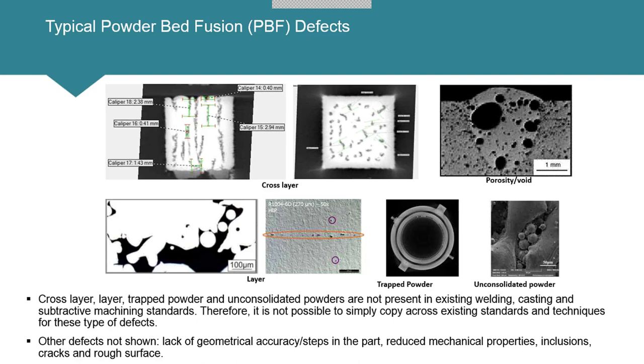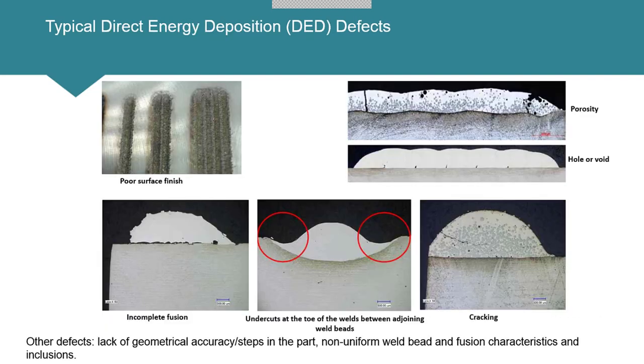Then you've got layer defects, and we also have trapped powder and unconsolidated powder. Trapped powder basically is powder that, for the geometry that was designed, gets trapped. And it may or may not be a problem, and therefore we may need to detect it. Then the difference with unconsolidated powder is the powder that you meant to melt, but for some reason, some process errors, or you just didn't do that. Now, in direct energy deposition, these are some examples of the types of defects that occur. You typically get poor surface finish, then you get porosity, and on top of that, it typically undercuts because of the size of the beads, and you could have incomplete fusion and cracking.